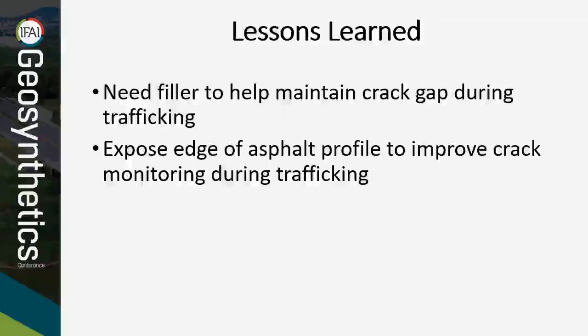Despite the lack of quantifiable performance data from this study, there were still a couple of valuable takeaways from the project. First, a filler should be used to keep the transverse cracks from healing together during trafficking. Sand is sometimes used for this purpose on smaller scale simulations.